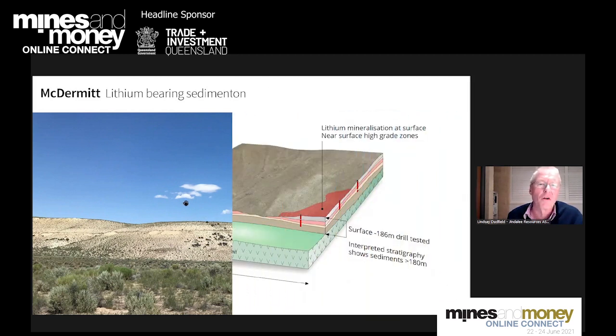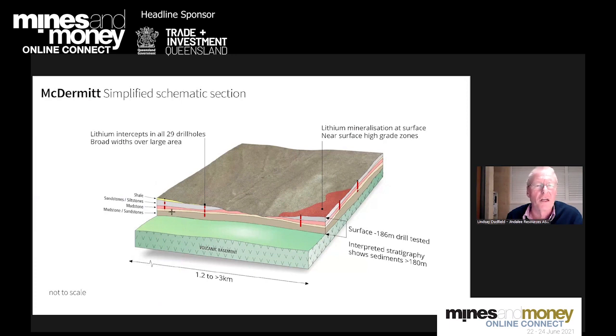And just a schematic showing that you've got these heterogeneous sediments that formed within the caldera, the McDermitt caldera, which hosts the lithium mineralisation, sitting on top of a volcanic basement. So we drill from surface, and we stop when we hit the basement. And on average, as I said, it's around 160 metres average thickness, but we've had up to over 180 metres of thickness of sediments. And every single hole that we've drilled has had broad lithium intercepts in it over very large areas. It's remarkably continuous, this mineralisation.